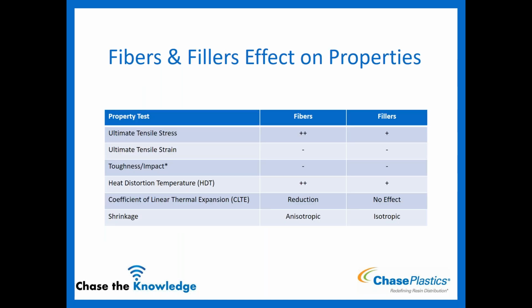So here's a quick little table to give you an idea of the properties and how they're affected. These are general; there are occasional rules of thumb or caveats, but generally speaking, fibers and fillers affect properties in these ways. Your ultimate tensile strength or stress, you're going to see that fibers are going to increase quite a bit. Your fillers might increase it a little bit. Your strain or elongation is going to be decreased with fibers and fillers. Your toughness and impact, this is where there's a little bit of a caveat, and we'll talk about it, but generally speaking, it does tend to decrease a little bit.